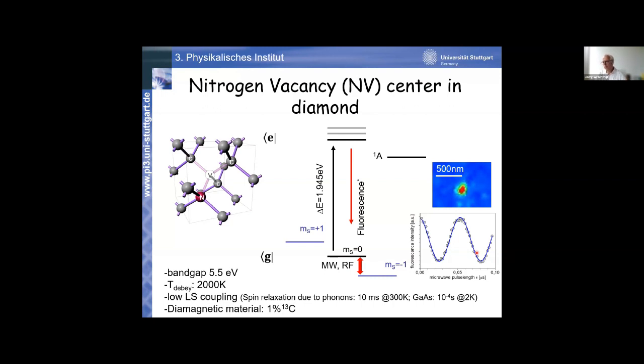People routinely observe these in all kinds of other systems, like atoms, gases, and so on and so forth. This, by the way, is done at room temperature. Typically, the Rabi frequencies we achieve here can be up to 100 megahertz or so. And I'm commenting on the spin dephasing time in a minute or so. But this typically is how an experiment looks. It involves optics and it involves microwaves. There are ways to do it in a microwave-free regime, but I'm not going to dwell on that very much, at least not today.